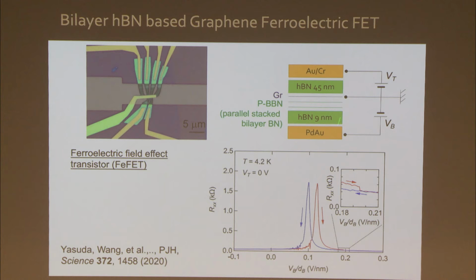And we can see that there is a typical resistance peak of graphene. If we go in one direction, if we sweep back in the opposite direction, there's a switch, and there's a hysteresis. Okay? And this hysteresis, as a function of electric field, is the smoking gun for ferroelectricity.